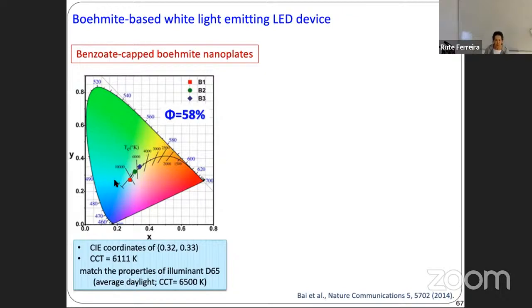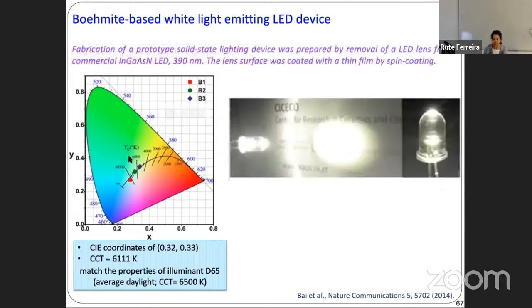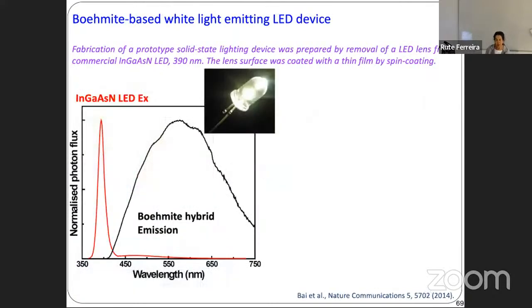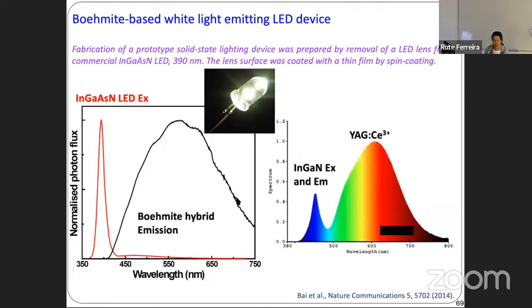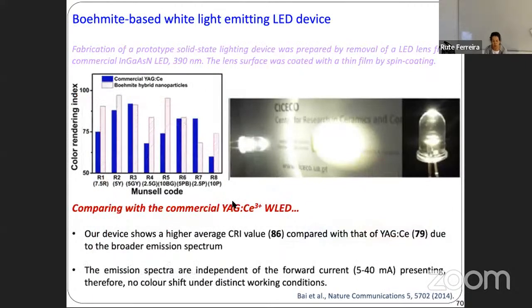in all the cases, we end up with white light. And here I show to you the prototype that was developed here. You can see very well the white light coming from our LED. Very interesting is that if we compare the indium gallium nitride LED that we are using in the excitation, plus the emission of the boehmite nanoparticles, with that of the commercial LED, we find in fact some similarities and some differences. And the main difference is that our spectrum is broader. And this is the reason why we end up with better performance numbers.